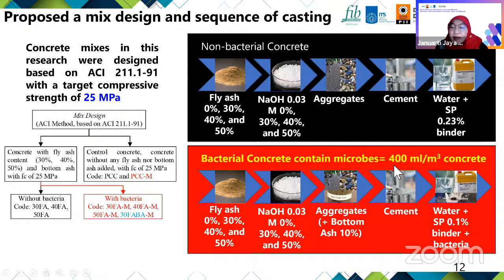The dosage is constant at about 400 milliliters per cubic meter of concrete. And because of the different workability of bacterial and non-bacterial concrete, we use a different content of superplasticizer. For non-bacterial concrete, we put 0.23% by binder weight, and we decrease the amount of superplasticizer to only 0.1% by binder weight.